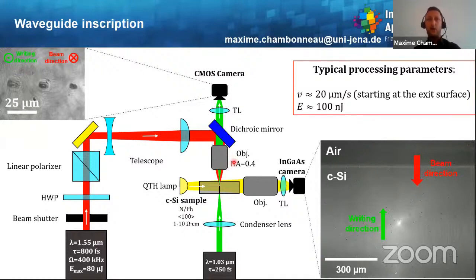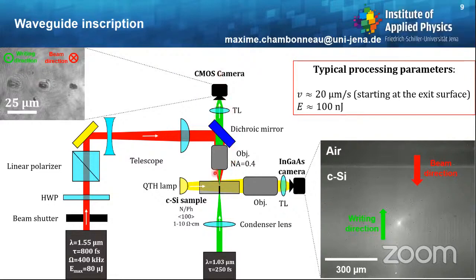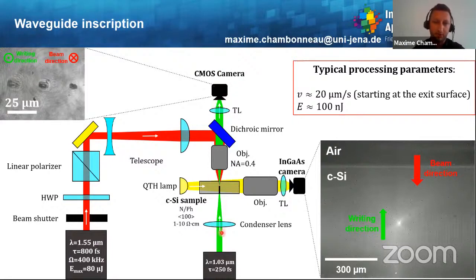This objective lens is also part of a microscope working in transmission, as shown here, relying on this green light, which allows us to take images of the interaction and monitor the interaction in the XY plane, where Z is often called the optical axis. So here we are perpendicular to Z. Besides, we have another microscope relying on white light emission, an objective lens, and an infrared camera, so we can see through silicon and monitor the interaction in the XZ plane. So you can see here a typical inscription where the bright part corresponds to the current laser focus.